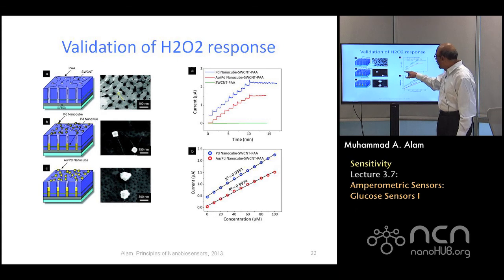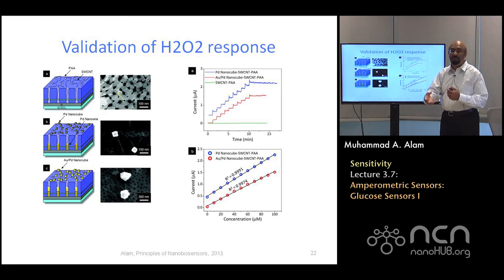And if you go ahead and start bringing different amounts of hydrogen peroxide into the solution, then we'll see that the current would essentially jump in steps, because every time you have a different concentration, remember the current in the amperometric electrode is directly proportional to the hydrogen peroxide, and therefore for every concentration there will be a response of current. It will stay flat for a little bit approximately. Then if you increase the concentration, it will go up, there will be more current, and so this is almost linearly proportional to the amount of analyte.